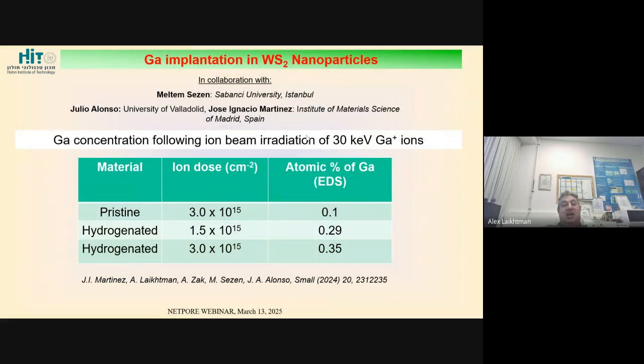This gallium implantation was performed using focused ion beams, and this was in collaboration with the group from Sabancı University, Meltem Sezen, who has now moved to the Netherlands. The theoretical calculations were performed with colleagues from Spain, Julio Alonso and Jose Ignacio Martinez. We used a gallium 30 keV beam in a FIB machine, and then we measured the concentrations of gallium by EDS in the scanning electron microscope.